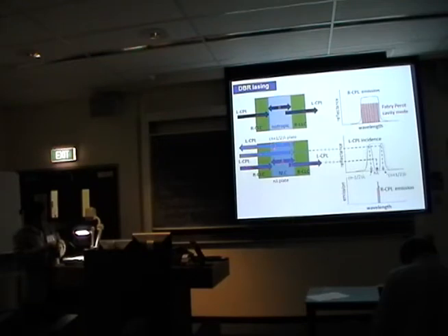However, if the thickness corresponds to an n plus half wavelength plate, then left-handed circularly polarized light changes to R, so it is reflected back. In this case, if we emit light inside, the right-handed circularly polarized emission is confined in this range, so we can lase here. So this is the story.